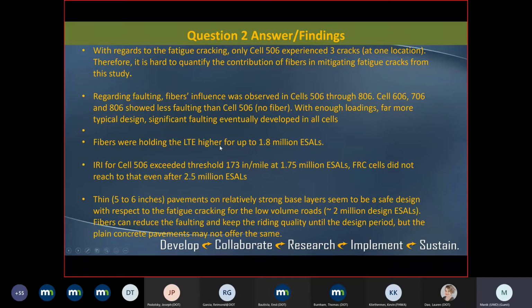Fibers were holding the LTE higher for up to 1.8 million ESALs. IRI for cell 506 exceeded the threshold of 173 inches per mile at 1.75 million ESALs. FRC cells did not reach that even after 2.5 million ESALs. So fibers contributed to keeping the IRI better.